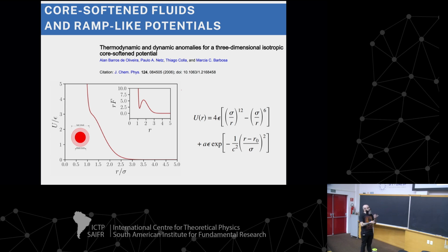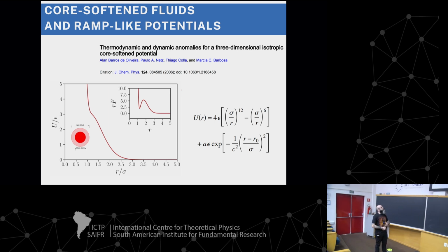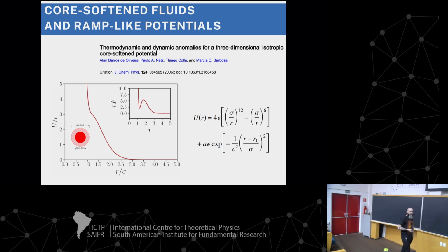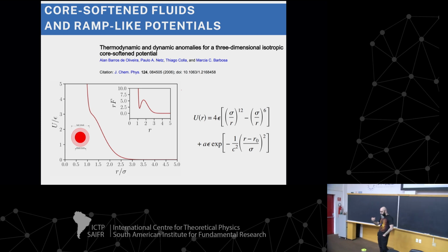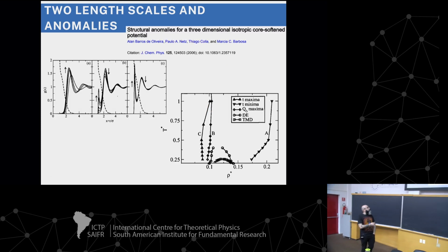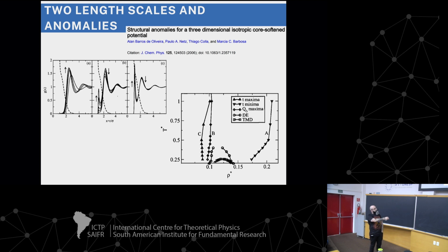OK, and why do we use the idea of a Lennard-Jones plus Gaussians? Because a long time ago, Marcia showed this potential yesterday. They proposed this model to try to understand the water anomalies. It's a really simple, really effective model. And remember the hierarchy: here is the TMD, the density or thermodynamic anomaly; here you have the dynamic anomalies, the diffusion minima and maxima; and here you have the structural anomaly, both translational and orientational.